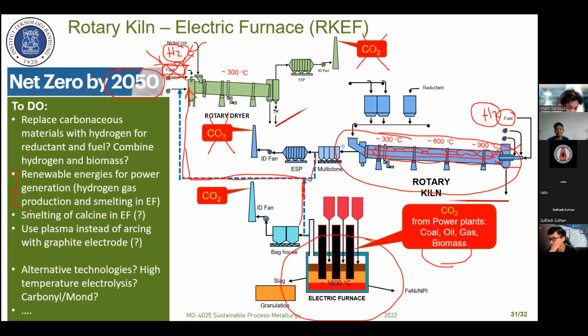And we now simulate this process in our laboratory, and we try to see whether the nickel oxide or iron oxide can be reduced 100% in the rotary kiln, and then we smelt it in the electric furnace, to see whether we can recover, we say, more than 90% nickel. We made this experiment in the laboratory.